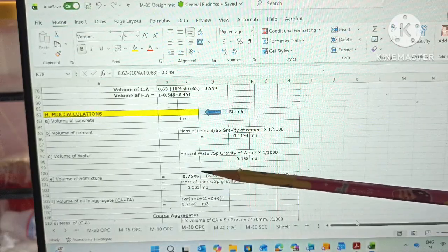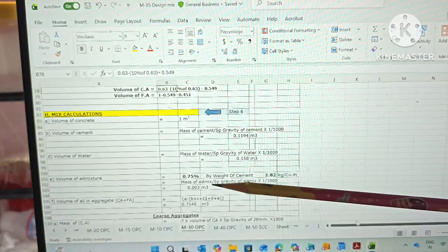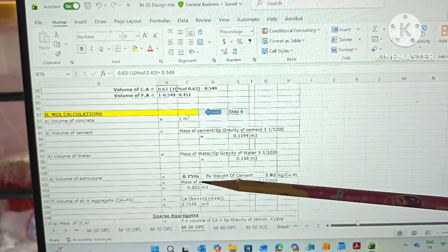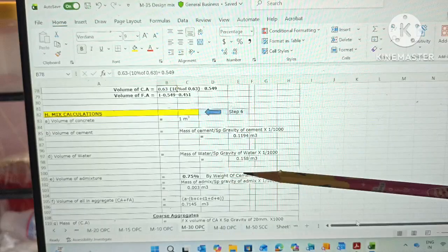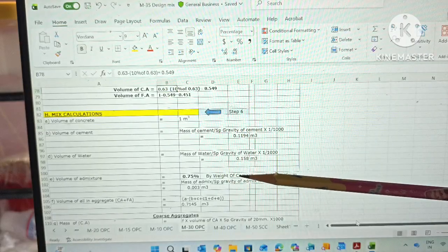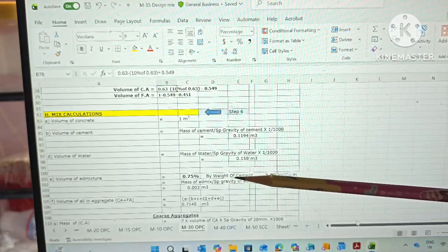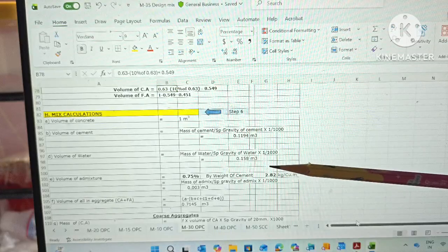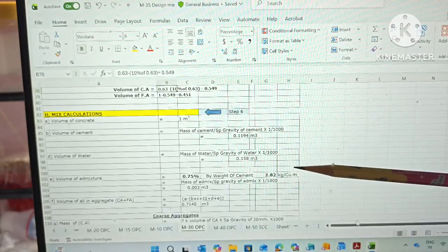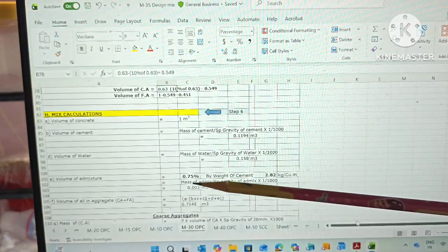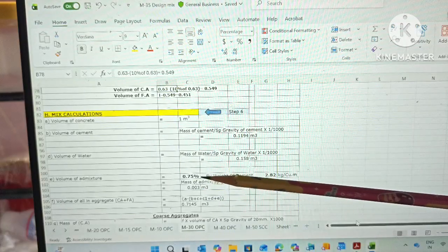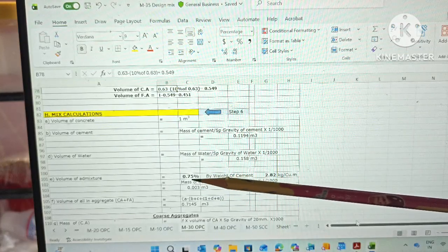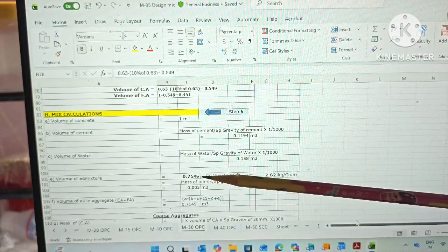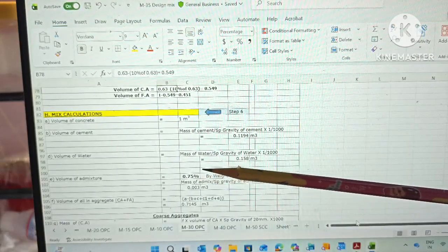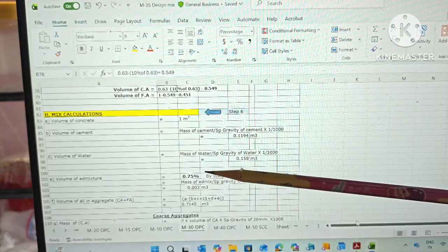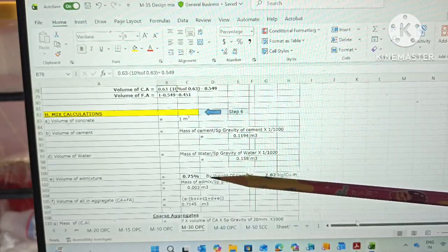Now in volume of admixture, how do we take the mass of admixture? For the mass of admixture, you need to take 0.75% of the weight of cement. That is, weight of cement is 376 kg. So 0.75% of 376 will give an answer of 2.82 kg per meter cube. Friends, dosage depends on your workability requirement. So I have taken 0.75. It depends on your dosage requirement, you can also take 0.85, you can take 0.9, you can take 1%. It depends on your workability requirement.